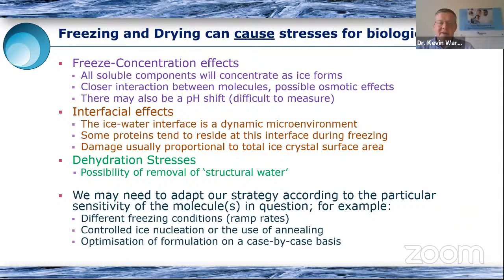So a good example here of freezing being a potential source of destabilization is what we call the freeze concentration effect. And now this will always happen in freezing. So the first thing that happens is that the ice crystals start to form. And actually what we're seeing initially is the formation of pure ice. And so the ice grows throughout the solution. And what it does is it forces everything else to become more and more concentrated between the ice crystals. So our active ingredient or organism will be forced into a smaller space. Molecules will be forced to interact with each other where perhaps they didn't in dilute solution. There might be osmotic effects on cells, and there can sometimes be a pH shift on freezing, which can be notoriously difficult to measure.